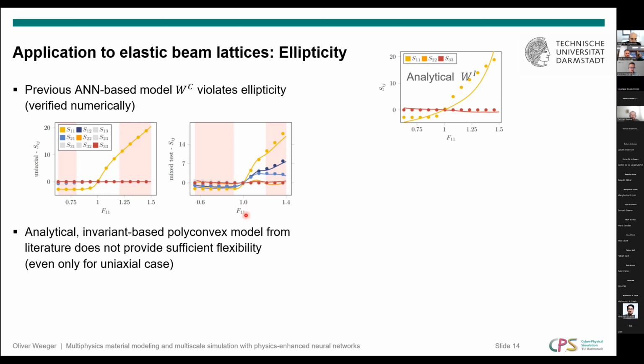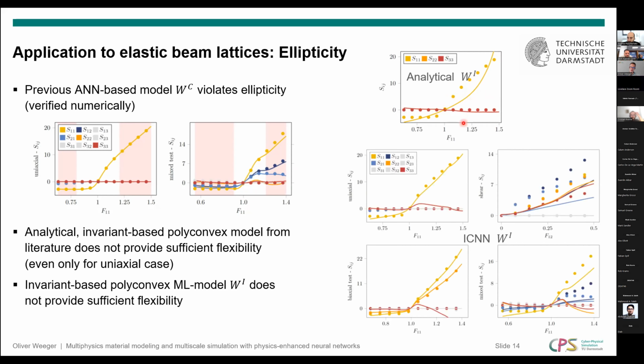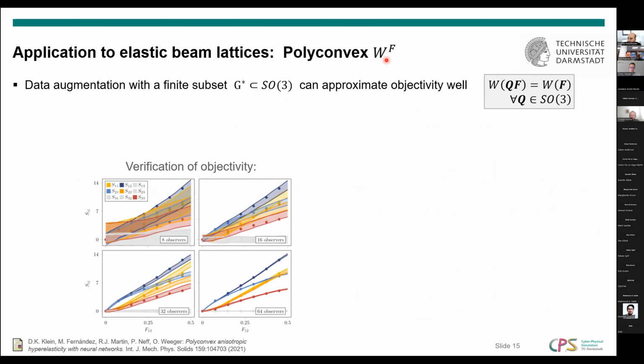Now, if we use an analytical invariant-based polyconvex model, we are not even able to approximate just uniaxial tension in a sufficiently accurate manner, because the behavior that these microstructures have is just too strange. Now we train our invariant-based input convex neural network model on this data. And it also doesn't look very good, especially here in the shear case where the model predictions, which are the continuous curves, are quite far from the data, which are indicated by the dots over here. And this might be the case because we have here a microstructure with a cubic material symmetry. And for cubic material symmetries, it is not clear actually how many and what invariants we have to use in order to describe the model. So the last resort now is basically this input convex neural network model W_F, where we use directly the deformation gradient.